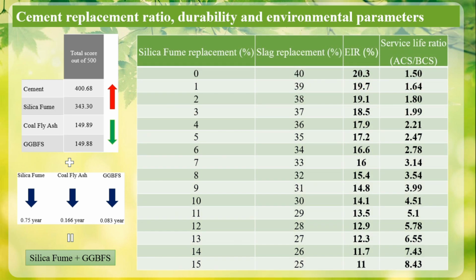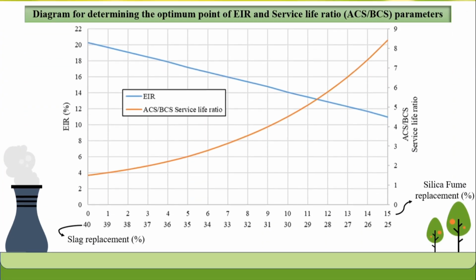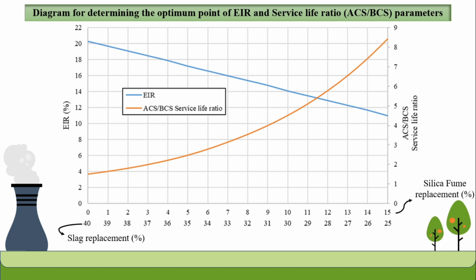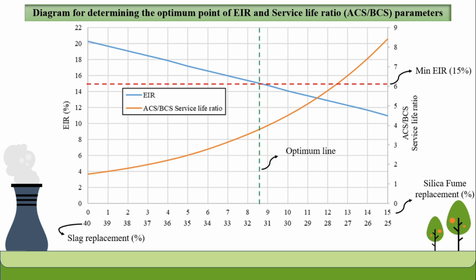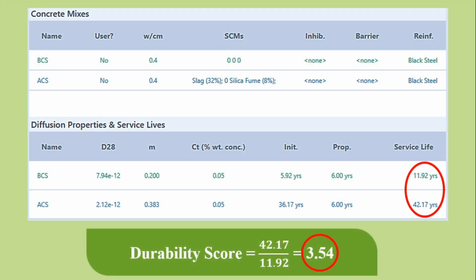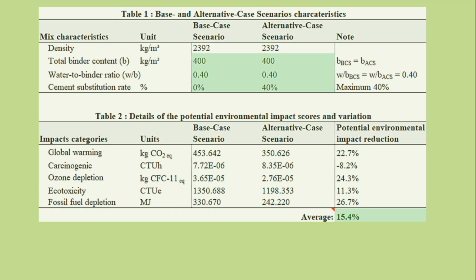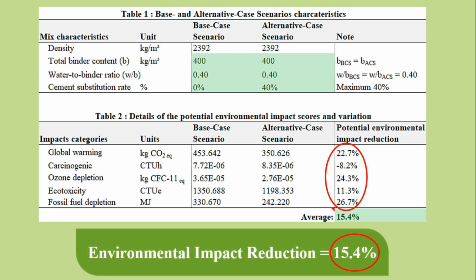Different replacement ranges of these materials were evaluated in the Ecoconcrete tool and Life-365, and the results are summarized in the table shown. An optimization diagram was developed based on the EIR and service life ratio from the previous slide. With the requirement of a minimum 15% reduction in EIR, the optimal point was determined to be 8% silica fume and 32% slag. For the selected combination, the durability score was calculated to be approximately 3.54. The EIR value was also calculated to be 15.4%.